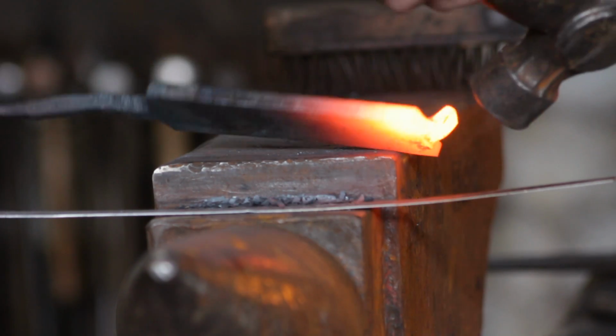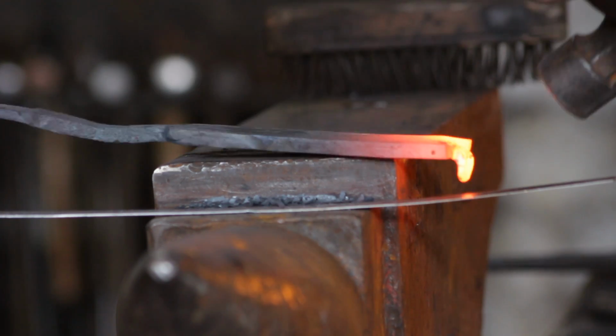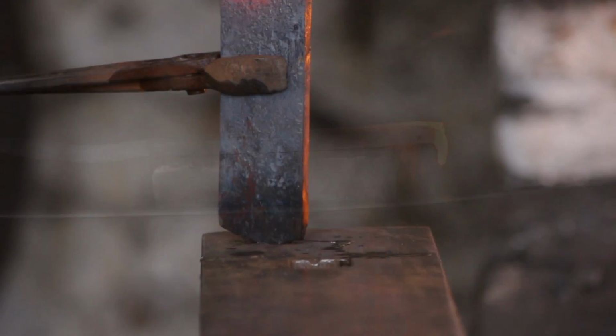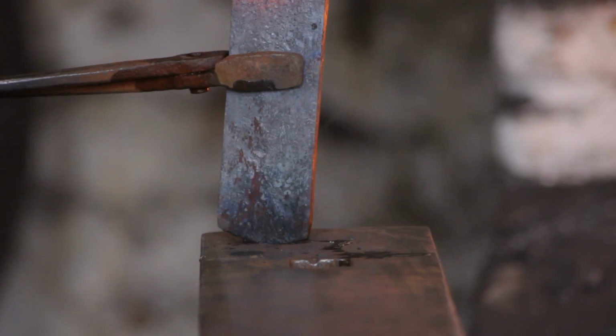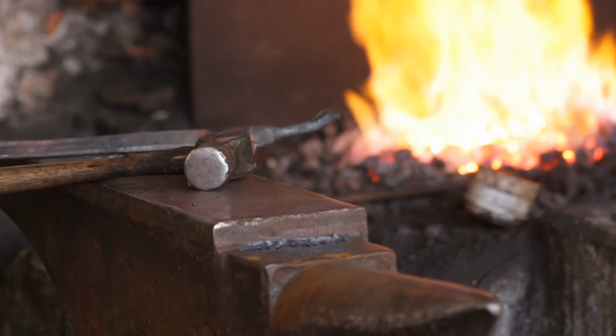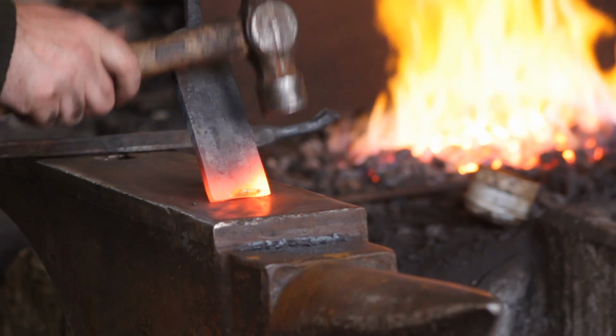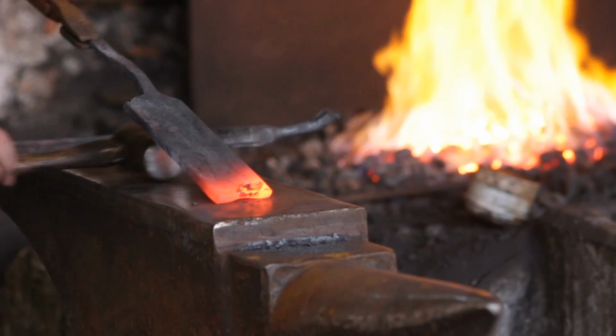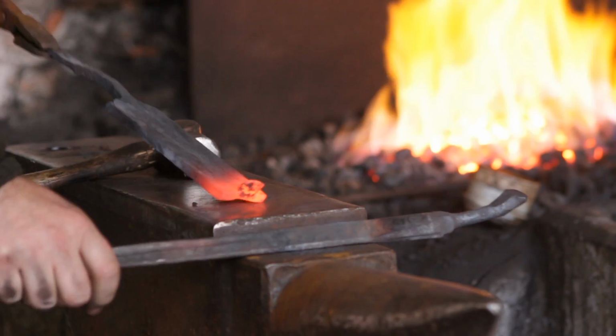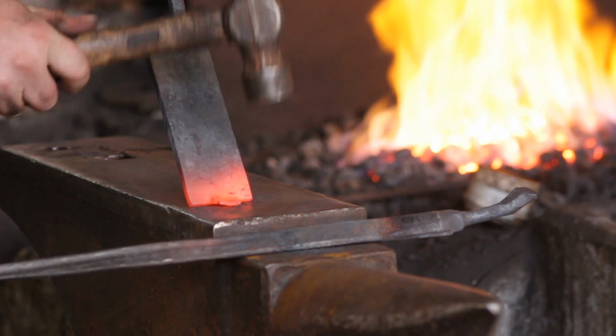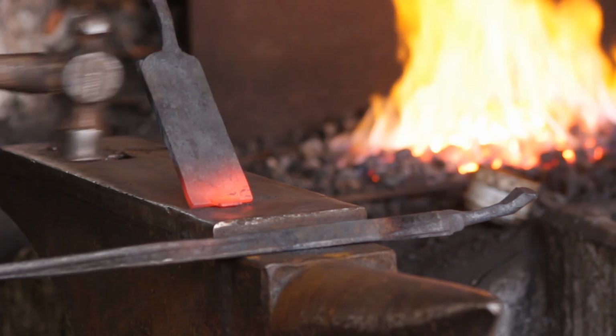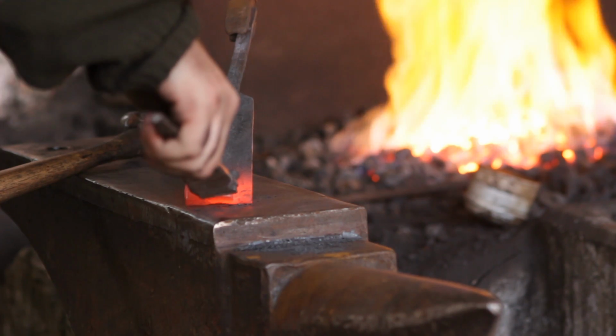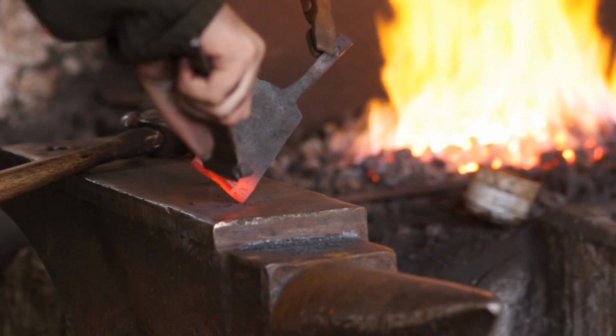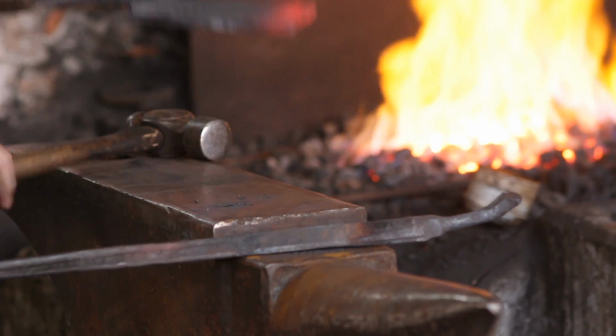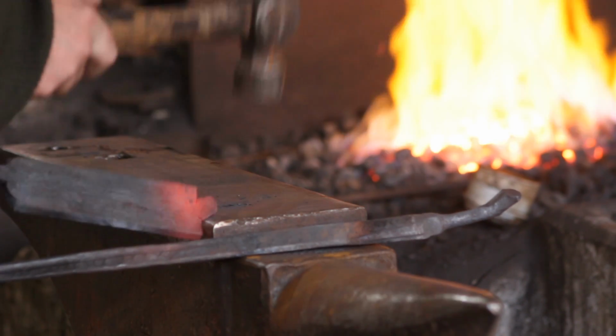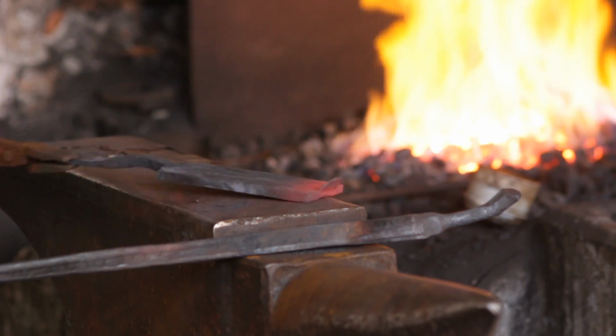and you then want to square it off. Now I went over to the pritchel hole for this and then missed the action on camera, so I do apologise for that, but the end result is that I've got a nice upset square corner on it. So then I will actually forge it back down and get it to a matching angle vis-a-vis the scarf on the blade, so that the two can combine without actually impeding each other, like so. So this tab will then be, once the scarf has been set to the billet, wrapped slightly around and welded up itself.